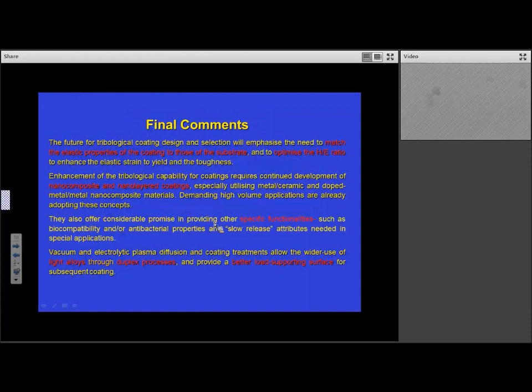So, slightly over Alex's prediction on the time, but hopefully we've got time for some questions. We require to match the elastic properties of the coating to those of the substrate. The enhancement of those properties is best achieved through nanocomposite and nanolayered structures, and we can achieve specific functionalities such as slow release attributes as well with these nanocomposites. And if we combine those together with another treatment to get a duplex process, then we get the possibility for even better performance. Thanks very much for listening.